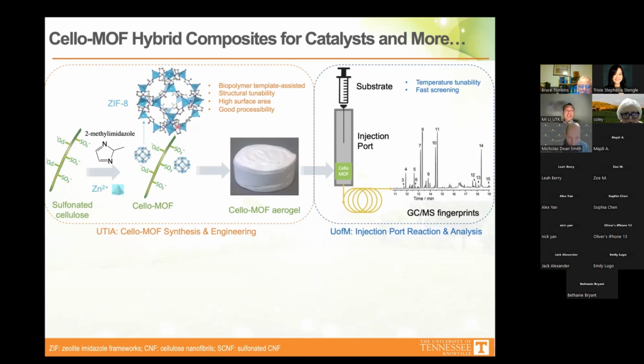Okay, so the MOF itself is good, but the problem is that the MOF is usually a nanoparticle in powder form. It's hard to process and apply to real life. So that's why the role of the nanocellulose or cellulose comes into play. As you know, we can make a lot of types of forms with nanocellulose, such as paper, filter, aerogel, hydrogel. For example, right here, this is a nanocellulose aerogel. So once you have this form, you load it with the MOF right here. It's a lot easier for you to apply to real life for purification, catalyst, and so on and so forth.